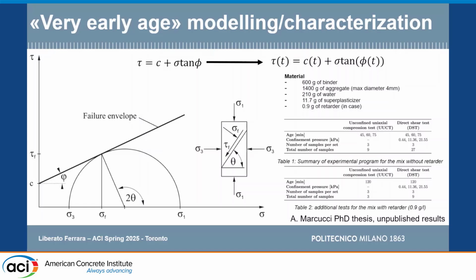And most of all, what kind of methodology, what kind of approach shall we use in order to describe the behavior of a concrete which is undergoing a fluid to solid transition? It's no longer a fluid, so we cannot model it any longer with a Bingham model, but it's still not a solid, so we cannot apply the usual finite element tools that we apply for solid structures. Actually the analogy between 3D printed concrete, between concrete in some stages of its life, and soil is quite well known. So we use the Mohr-Coulomb criterion, which is typically used for cohesive granular soil.